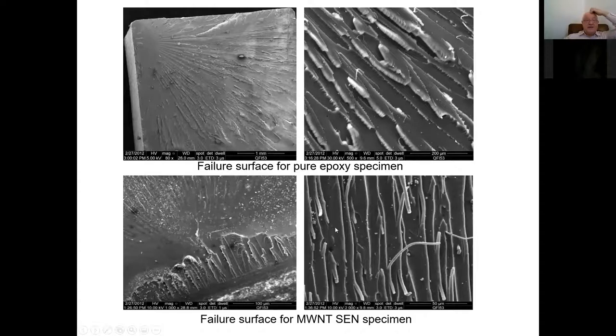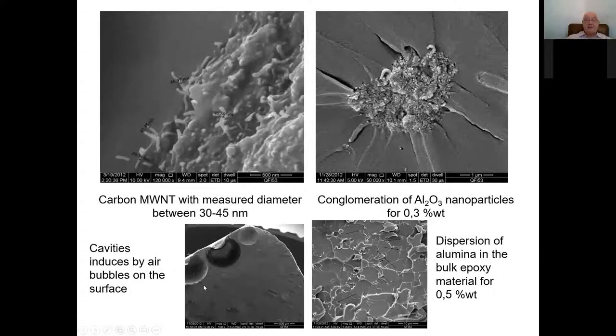So how does the failure surface of such epoxy specimens look? This is pure epoxy. This is the failure surface for a single edge notch specimen with carbon nanotubes. This is the initial crack after hitting with a blade. And here what you see are the carbon nanotubes dispersed somehow. Well, how they are dispersed, in some cases, quite poorly.